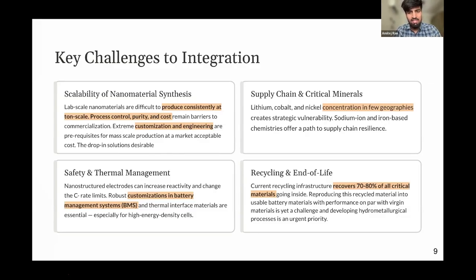Currently, for lithium-ion batteries, the recycling infrastructure recovers 70 to 80% of all the critical materials, which is again a very good figure, given that we started with, say, 20%, say 10 years back. Right now, people use different routes like hydrometallurgical routes, which can recover this much amount of materials. Using pyrometallurgical routes, the yield is less than 40%. So that is not scalable at all.